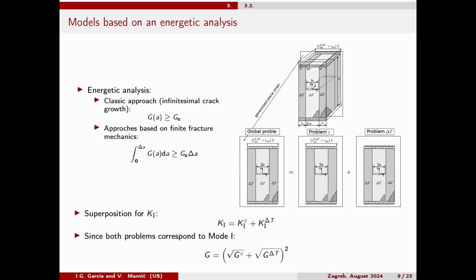What happens with the theories based on an energetic analysis? We can try to do the same superposition. We assume actually the same partial problem, but just with a crack that we assume is symmetric and in pure mode 1, perpendicular to the load direction. And with that, we can assume this superposition for the stress intensity factor. And as it is in pure mode 1, we can go to this superposition for the energy release rates.